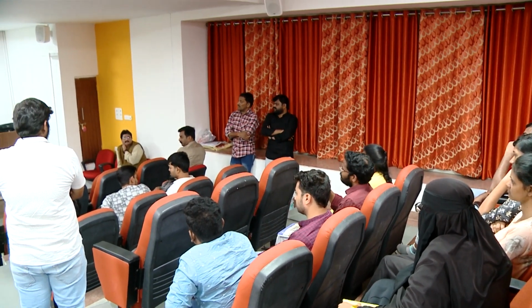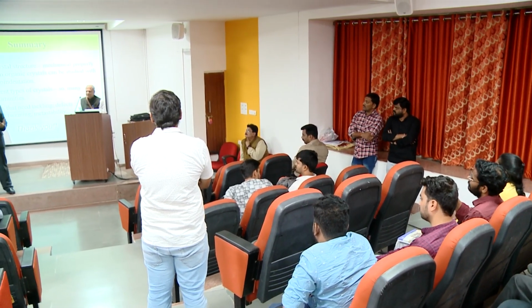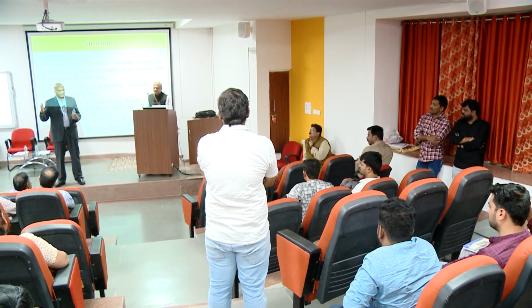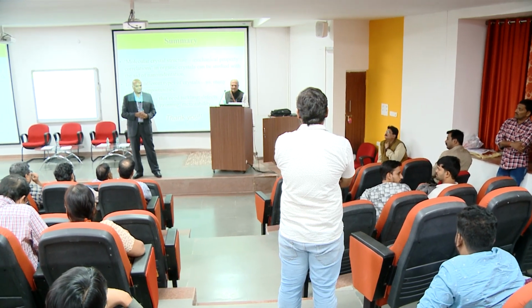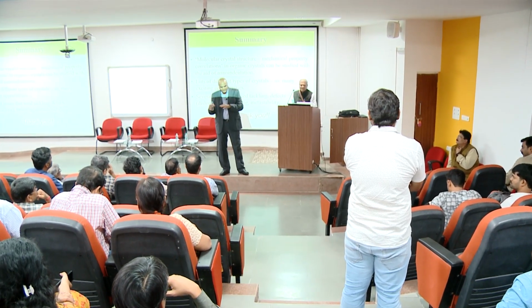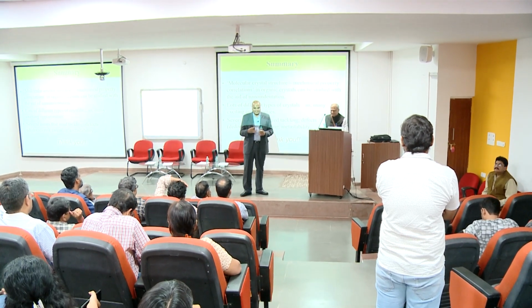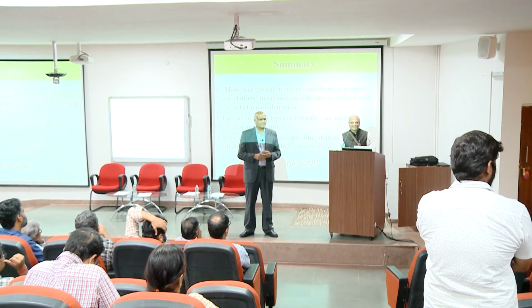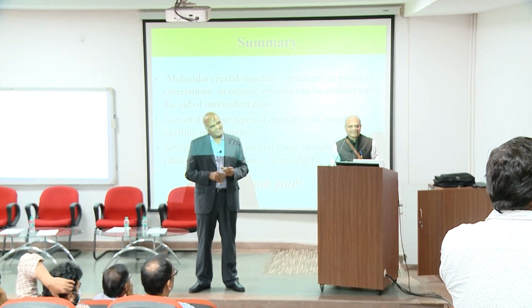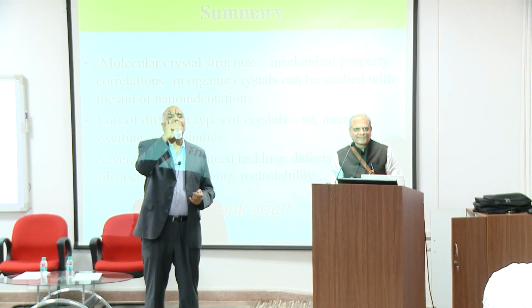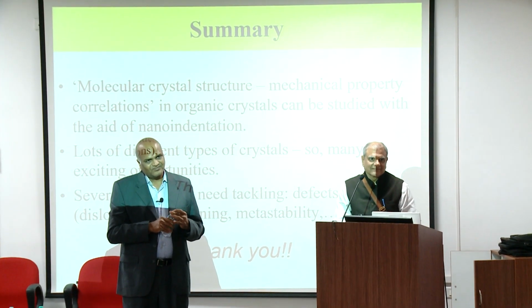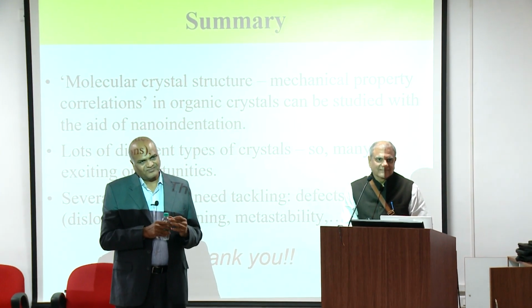I think DFT calculations look at density of states and things like that. In explaining, you have to do all the various experimental techniques, right? Raman gives the shifts that are associated with the stretching of these copper-copper bonds or interactions, and DFT calculations also confirm that. Sir, but if you look at the actual mechanism of bending, the atom movements are so tiny. How do you capture those tiny movements in the theoretical calculations you are performing?